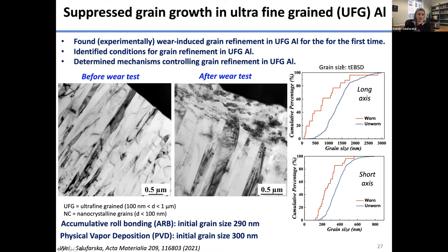And so we also used transmission electron backscatter diffraction, TEBSD, to study grain size distribution. So this shows the distribution of grain sizes, the blue one is before wear test and the red one is afterwards. So you can see it shifts to the left. So we see the grain refinement.